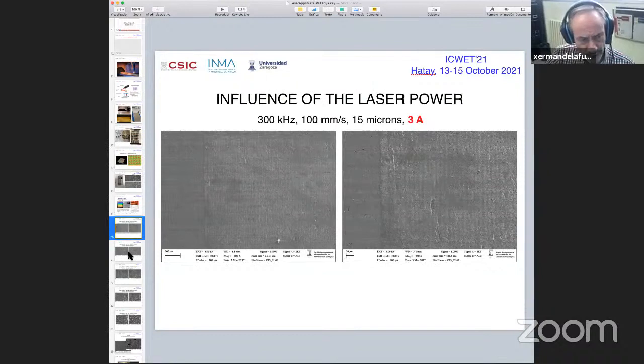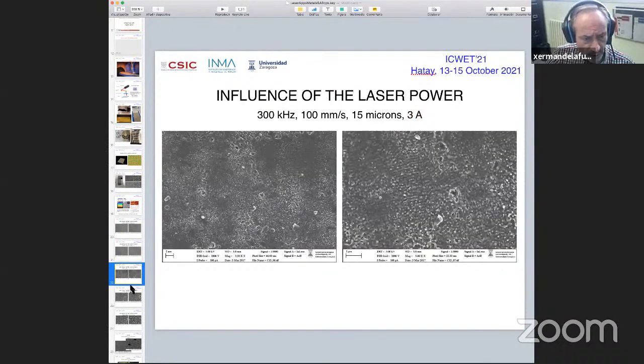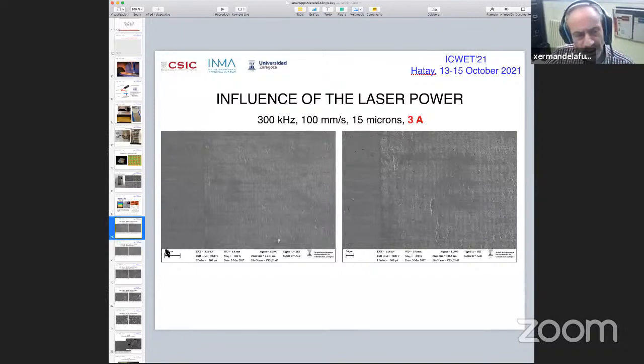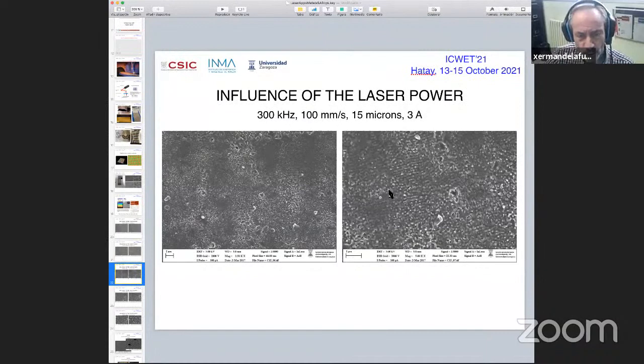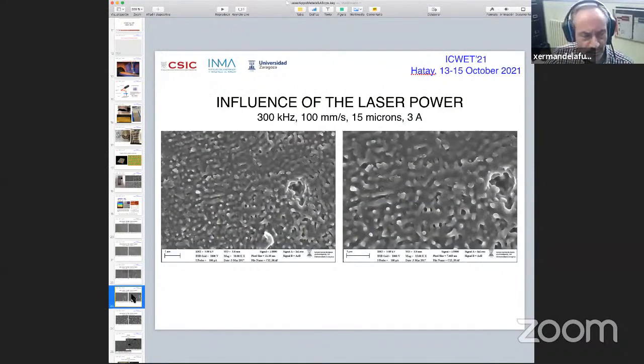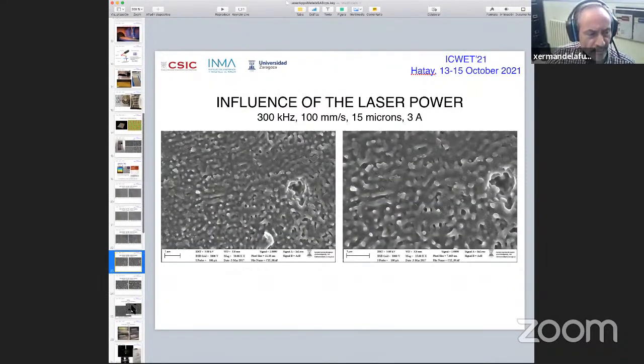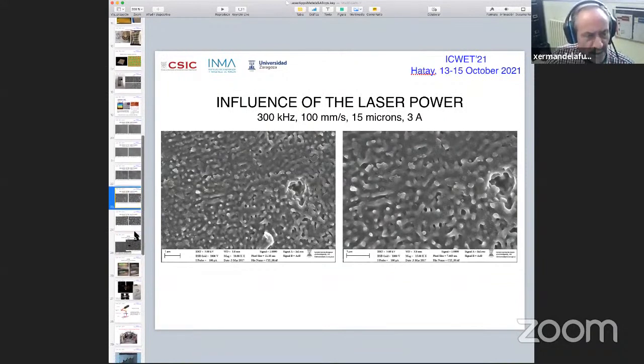This is a sequence that shows how, on a specific surface, we can change the structuring. Basically what I can show you here is that initially you don't seem to see much of a nanostructure, but as you increase the power of the microscope, you can see these nanostructures. This is only 2 microns, and these nanostructures are well below 1 micron, and they are about on the optical range of the electromagnetic spectrum. So in this case, again, between 400 and 500 nanometers in periodicity.